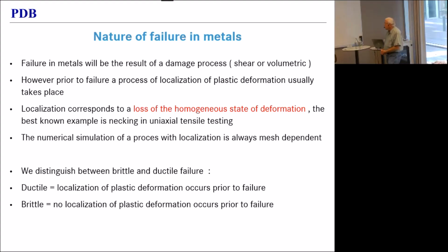Now, we usually distinguish between brittle and ductile failure. Ductile failure means that you localize prior to failure, and that means you will have to regularize. Brittle failure, in my terminology, is that there is no localization prior to failure. So you break before your neck, and then there is no need for regularization.